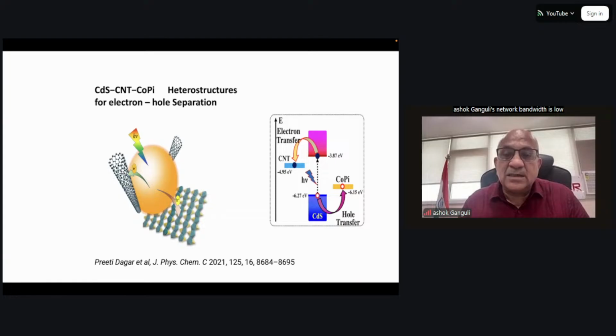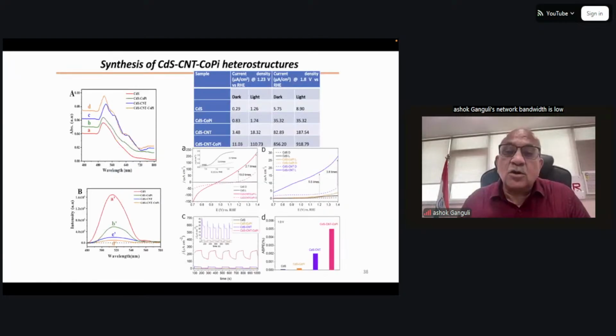These are all different measurements to show that the ternary system with the hole sink and electron sink will have the highest current density. Okay, 856 microamperes per centimeter square, but the only cadmium sulfide gives only 5 microamperes. So it is several hundred times more when you have got the hole sink and the electron sink. And there are other data here. I don't have time to discuss it.